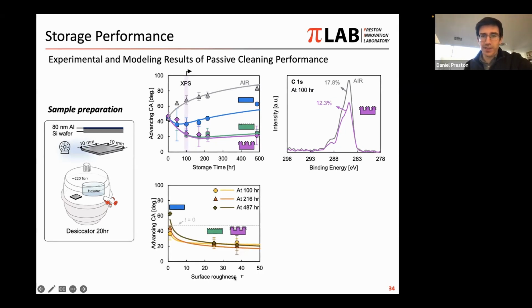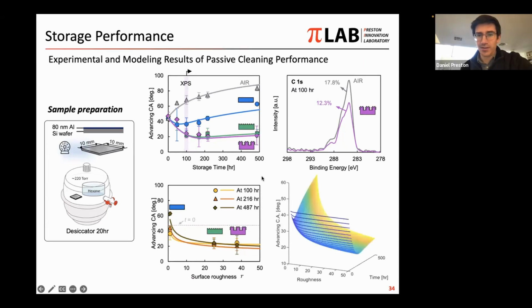You can look at this in a different way. For example, looking at the effect of the surface roughness on the contact angle at different times. And over time, we find that these higher levels of surface roughness result in a steady or stable level of lower contact angle, even pushing towards hundreds of hours of storage time. And our model, all of the curves in these two left plots are model curves, actually allows us to predict the full design space of what the roughness should be at different levels of time to predict this cleaning performance for samples stored in these types of containers.